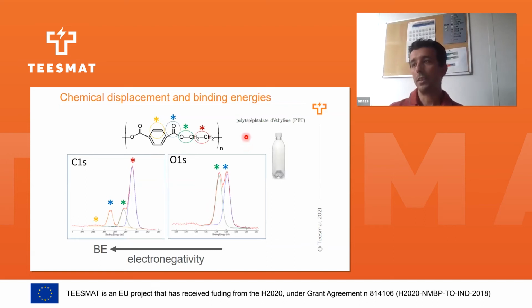Now we go to this peak. This is polyethylene terephthalate, which is what we have in every water bottle: PET. And this is the XPS signature of our PET. And the PET chemical composition is like this. We can see that we have an aromatic group, we have a carboxylic group, and we have an alkyl group.